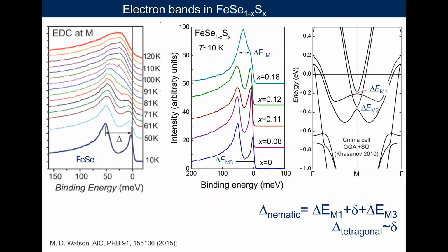For the electron bands, things are a bit more complicated. As I said, we should have 2 electron dispersions, and if you go inside of an orthorhombic phase, one should split the various crossings here, which were degenerate in the tetragonal phase. And these are the signature that one can see in experiments. It's a very unusual splitting between the 2 features in the ARPES spectrum.